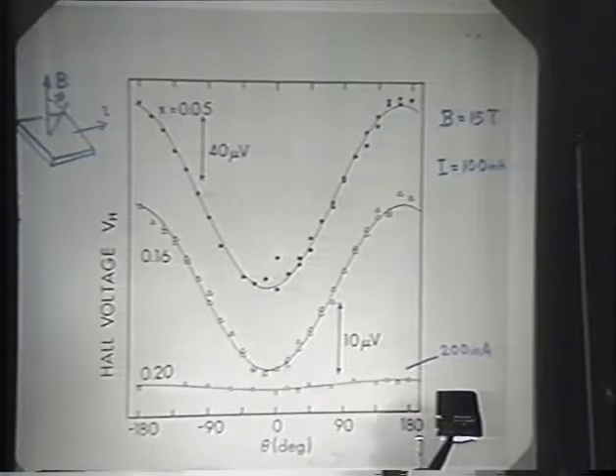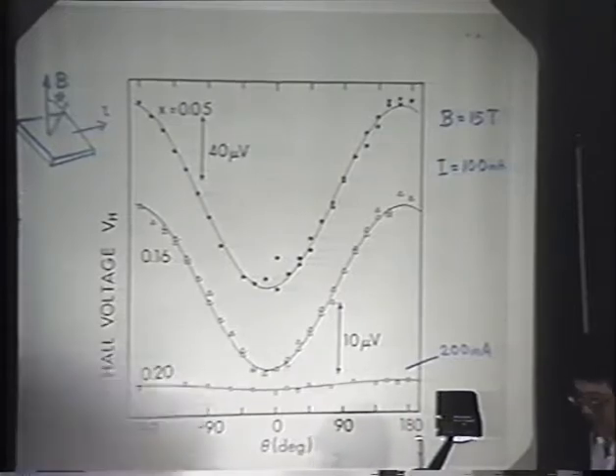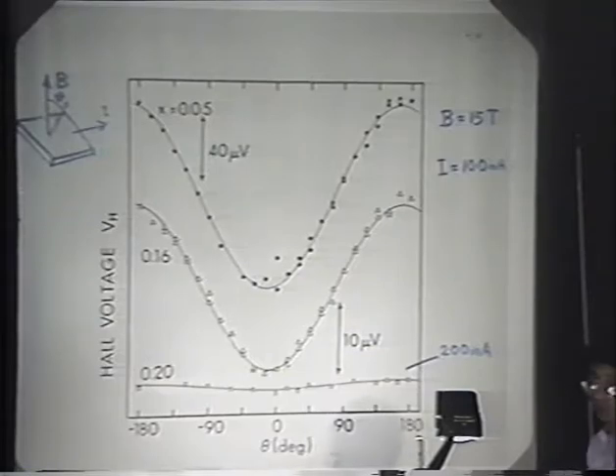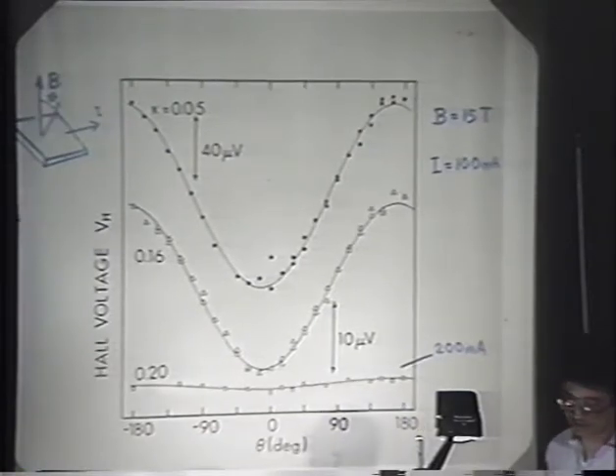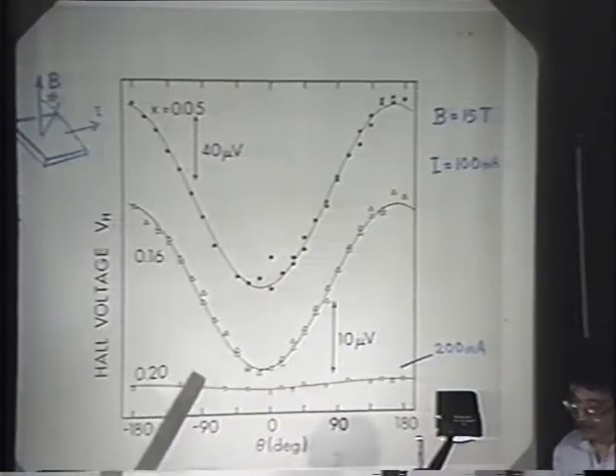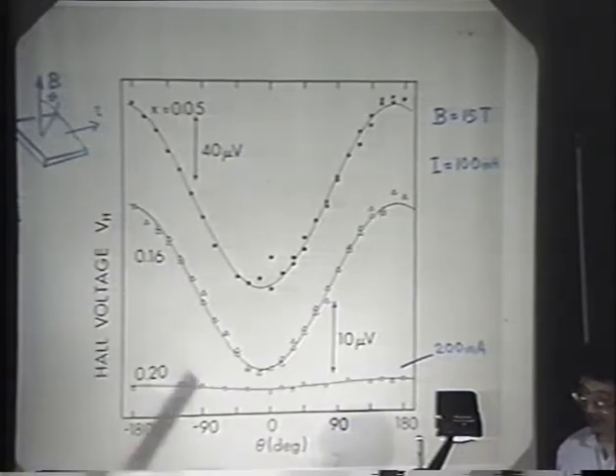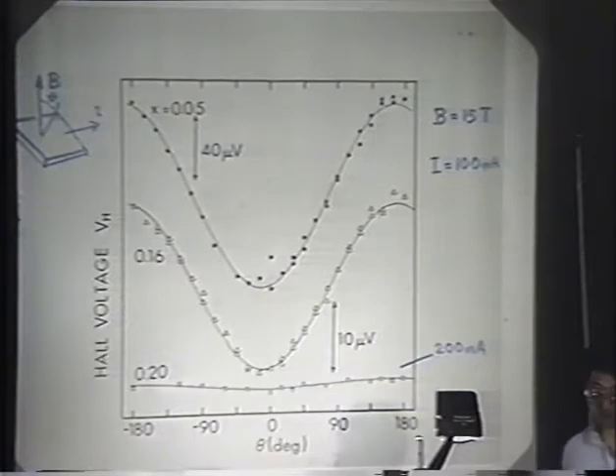These are 2 samples, and that's characteristic of the Hall signal. The background rho XX contamination turns out to be approximately twice the size of the Hall signal. And you can see that in going from 0.05 to 0.16, it scales somewhat. But then in going from 0.16 to 0.2, the signal vanishes even when you have doubled the probing current.